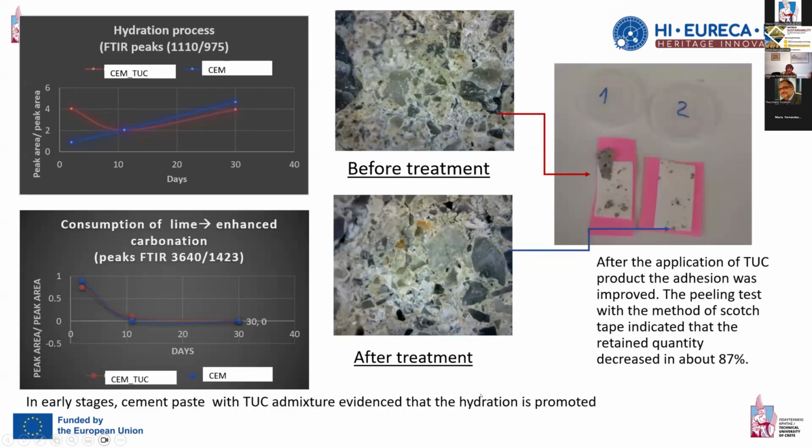Of course, after the application, we have tried to assess if the structure was reinforced, and according to a peeling test, we have seen that less material was removed after the application of our product compared to the initial removal of material.